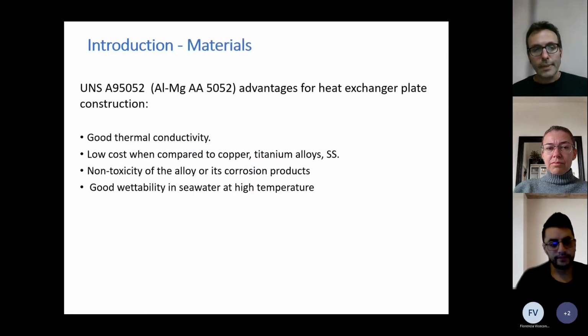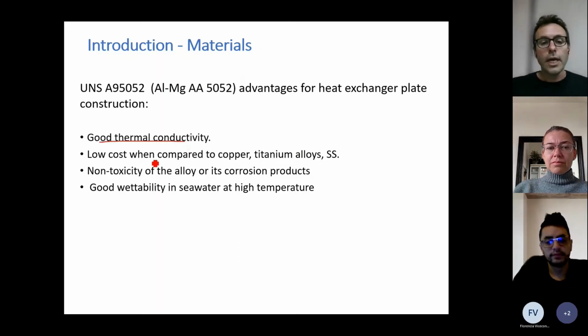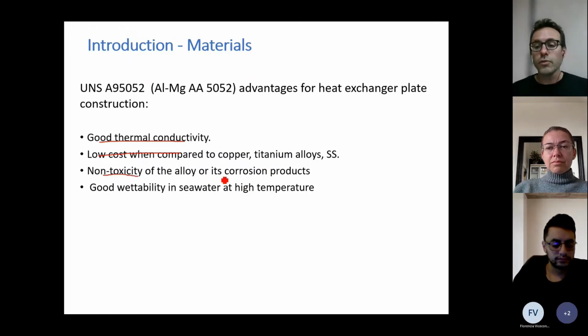And the alloy selected, besides being corrosion resistant, must have good thermal conductivity, so it can transport this latent heat of evaporation. It must have a low cost, especially when compared to other candidate alloys. The corrosion products cannot be toxic because you're supposed to be able to drink this water at the end of the day. And it must have good wettability in seawater at high temperature, right?